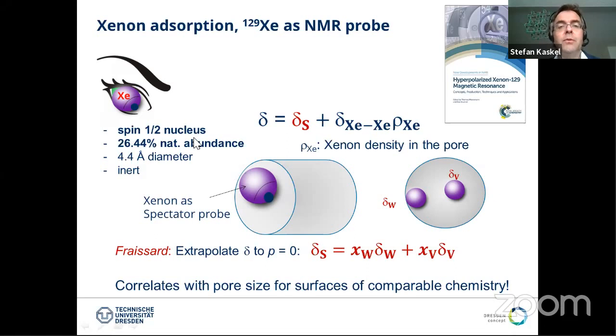Because the chemical shift of the xenon NMR probe also depends on the pore wall interactions. This is basically this term delta S here in this equation. Delta is the chemical shift. And then it also depends on the xenon-xenon interactions. And they are, of course, dependent on the amount of atoms that interact, and also the density of the xenon plays a role here. And so ultimately the chemical shift is also pressure dependent.